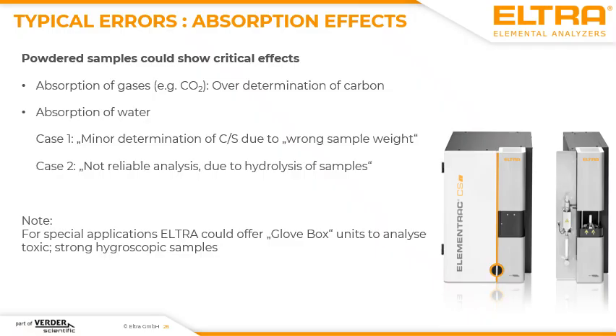When you have good luck, then this effect is reversible and you can just dry the sample and then measure it again, and then you would get correct results. But some samples, for example, which are especially used as hygroscopic samples like salts, or maybe samples which are used in battery production, you are also facing a different effect, because you don't only have the absorption of moisture, but you also have a hydrolysis of samples, which means, for example, lithium-based samples could really react with the water content which is in the atmosphere and falsify the results.